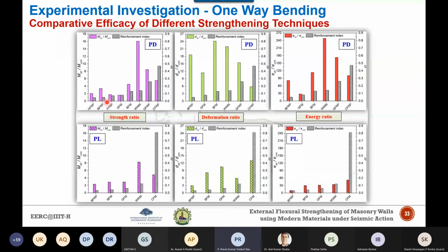And the failure is basically occurring in case of the rupture. Whereas when the walls are strengthened using very high tensile strength fabrics, then there is a problem especially related to the debonding failure mode. But here all the test results have been drawn with respect to the rupture failure mode, and therefore you can see that welded wire mesh is performing very well in case of the strength,